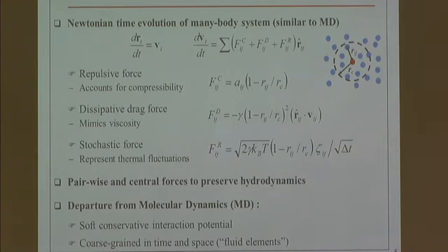So this is very important. This is the so-called DPD thermostat. Essentially, these two forces constitute the DPD thermostat. And if you look at the literature, there's use for this. We can, for example, replace this conservative force with Lennard-Jones and then use this DPD thermostat to model real atomistic systems. But again, the main advantage is that this is a momentum-conserving thermostat, which helps us if we want to model hydrodynamic systems.